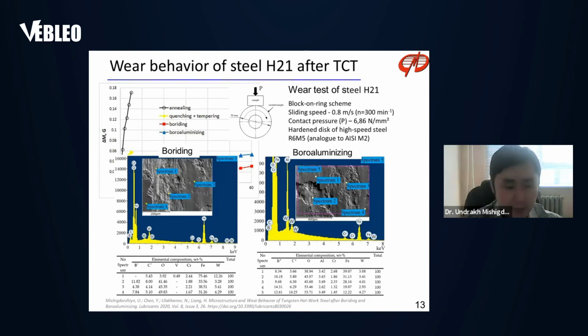After boroaluminizing, it is necessary to say that galling is the principal mechanism of wear, and after boriding, low welding tendency resulted in high wear resistance. EDS analysis showed the presence of a high amount of oxygen in both cases, which is probably a signal of tribo-oxide presence and formation during the wear test.